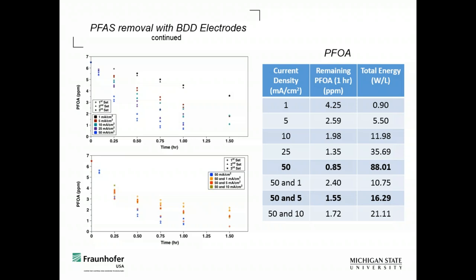But so what we are trying to do, since we can't use this experimental model like I showed, we had to somehow do this experimentally. So when we did these tests of varying current density, we found in the first 15 minutes there was an advantage of using a higher current density, like 50 milliamps per centimeter squared. But then we looked at the slopes of all the lines, or the rate constants of the lines thereafter, and they were all similar. So we thought, okay, well, why don't we just use the high current density for the first 15 minutes and then reduce the current density thereafter and see what we get.